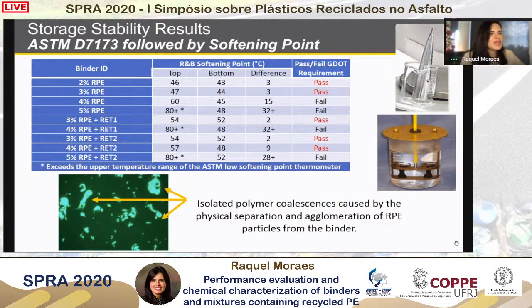So you see that on the first four samples, we have the base binder modified with the recycled plastic by itself in 4 different percentages: 2, 3, 4, and 5. And then we have the same blend of the binder with the recycled plastic modified with one type of terpolymer, that is the RET1, and a different type of terpolymer, that is the RET2.